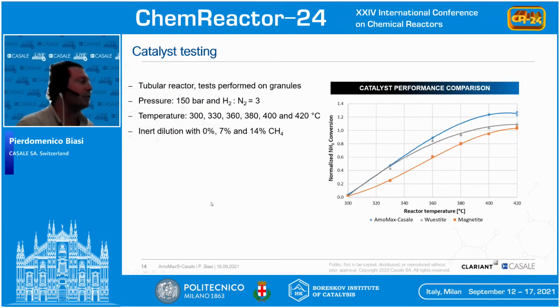So first of all, to test and compare the catalysts, we got a lot of formulations from Clariant, and we started to test them in a tubular reactor at high pressure, representative of the industrial conditions, at different temperatures to study the kinetics, but also with an inert dilution of methane in the gas stream, because this is really important in the feed stream, both when you calculate the kinetics and when you have the operating conditions with the catalyst.